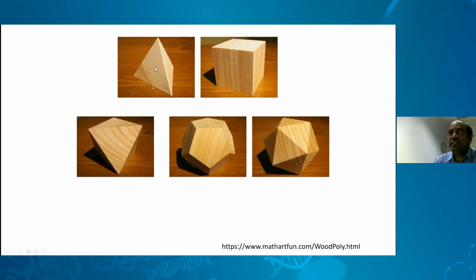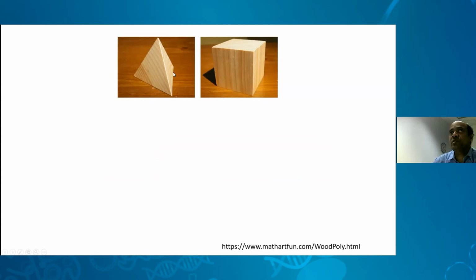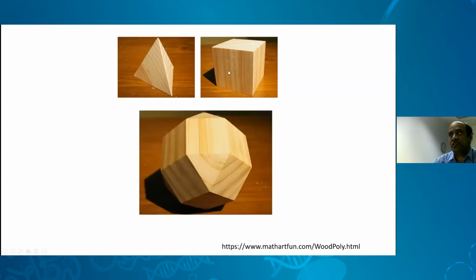have four facets, you get a tetrahedron, and with eight facets, you have an octahedron, and so on. So the unique thing about these five I show here is that they all are similar, with one type of facet, but it can also have a mixture of both the triangle and the cube, like this structure. One can have a complicated structure with a mixture of two types of facets.